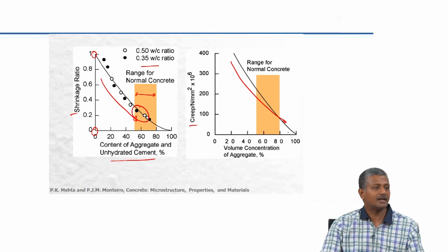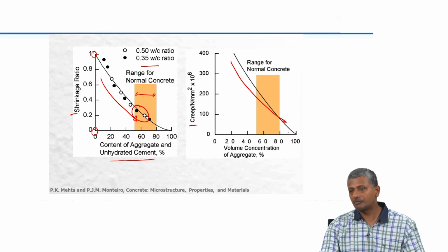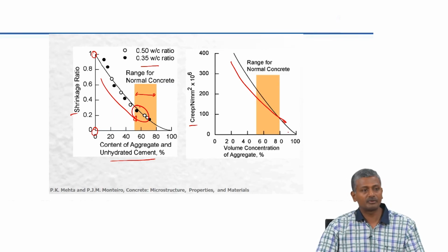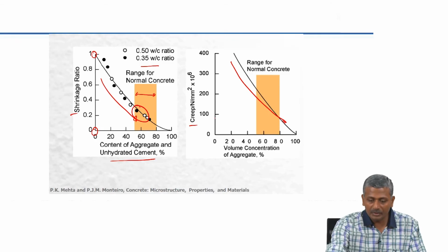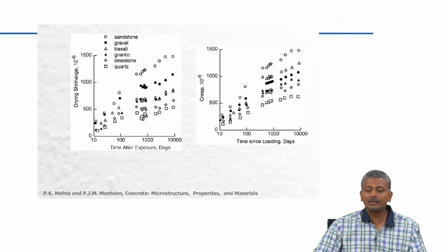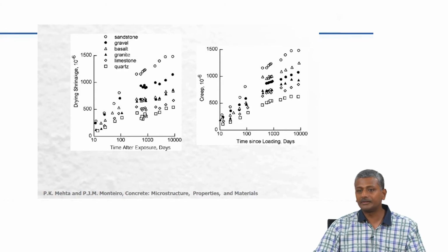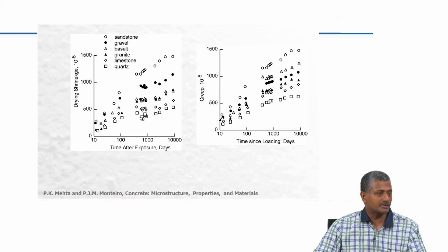So, the higher the aggregate content, the lower will be the creep, but for the normal concrete, you will get about 25% of your paste creep. So, 100 as compared to 400. Again, this is actually research data that shows you the creep with respect to different types of aggregate. Again, we talked about this earlier also from the perspective of the interfacial transition zone characteristics, right.